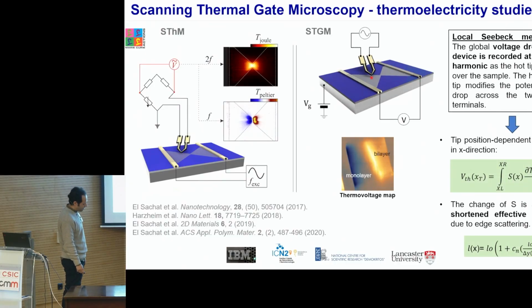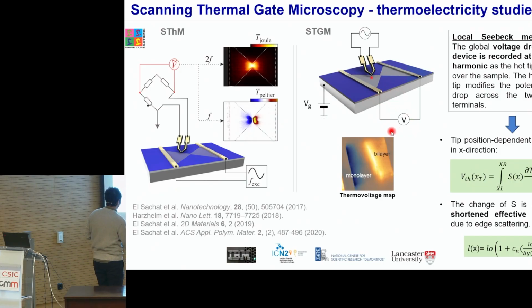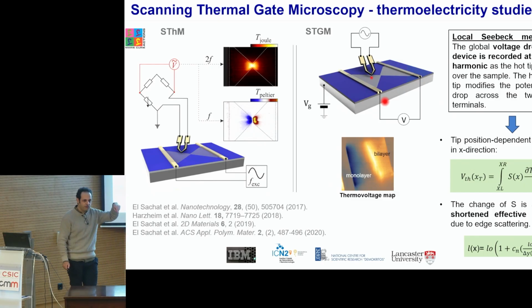To do this, we employed scanning thermal gate microscopy, which is a different version of scanning probe microscopy, where we have a three-terminal device and we use the tip as a hotspot, and we scan the tip over the sample. Here we connect the two-electrode devices and measure the thermovoltage, with the tip on top of our flakes. As the tip scans the sample, it modifies the potential voltage drop across the two terminals, and we can have a thermovoltage mapping. Here you see one example of a thermovoltage map in monolayer and bilayer graphene. From this map, we can extract the local Seebeck coefficient of the materials.